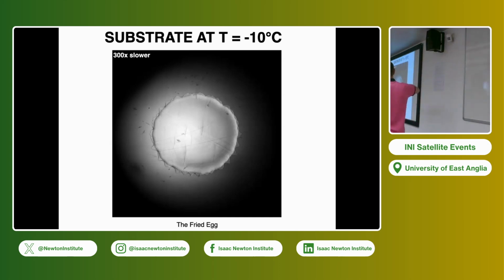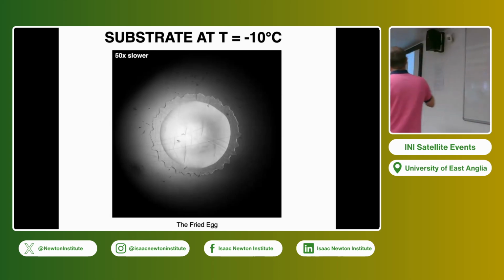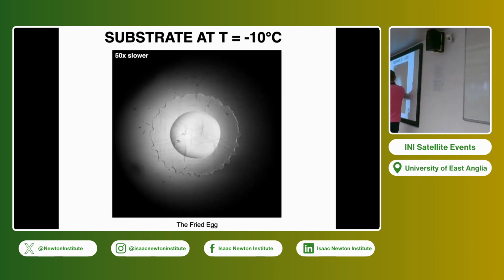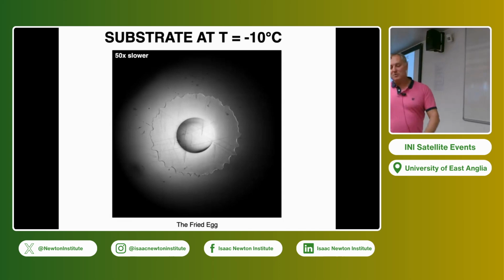So what happens after you reach the maximum radius, you have a dynamics where you have relaxation of capillary waves of your system, and the contact line somehow is pinned on this ice edge. And then if we run the movie again, you see that the liquid is retracting on ice, and retracting in a very nice circle in that case. And if we continue the movie again, I stop the movie again, we have now a thin layer of ice, plus a hemispherical shape of water. And if we still continue the experiments, this water spherical cap will solidify.